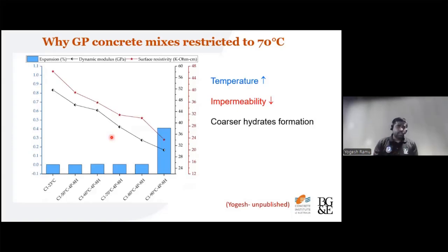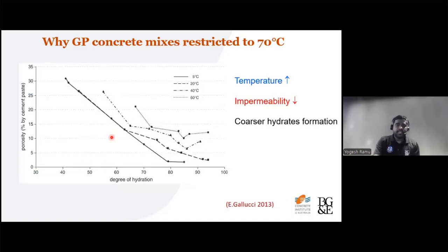So as the temperature goes higher, the impermeability of the concrete is reducing, which again, as I mentioned earlier, is due to the coarser hydrate formation. That's why, if the concrete is expected to go beyond 70 or so, it's better to have SCMs blended in it. So it's not only me who did this. Some other researchers also tried to explain it with some other test methods.